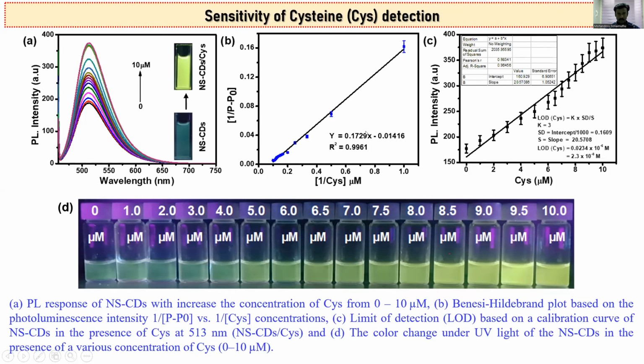Furthermore, we have to calculate the limit of detection from the photoluminescence intensities. For 0 to 10 micromolar, we can calculate from this method, it's found to be 23 nanomolar. So actually we have to take a wide linear range from 0 to 10 micromolar. We can get the calculation method, and the limit of detection is 23 nanomolar. So the result confirmed that the carbon dots with cysteine have good sensitivity and also good selectivity, and we can get a low limit of detection in aqueous medium.